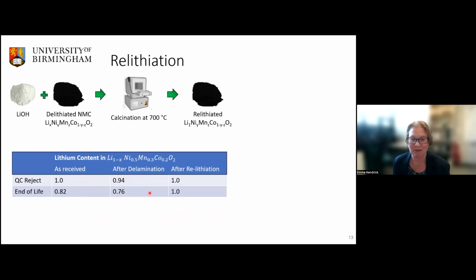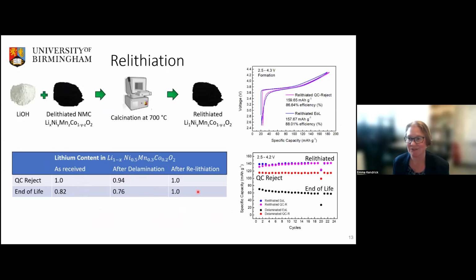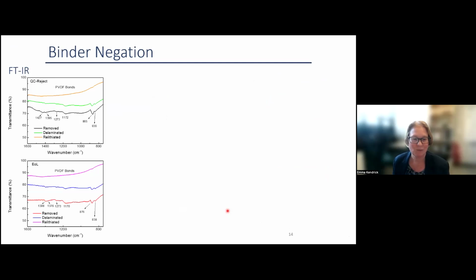After delamination, we lost a bit of lithium. We could reinsert these into the materials. And actually, both of them showed some pretty decent specific capacities, reversibilities, and cycle life, as you can see from this. Still need some work on trying to improve the delamination process, however. One of the issues that we do have is the binder. This just shows you that we have PVDF in this binder, both QC reject and the end of life.